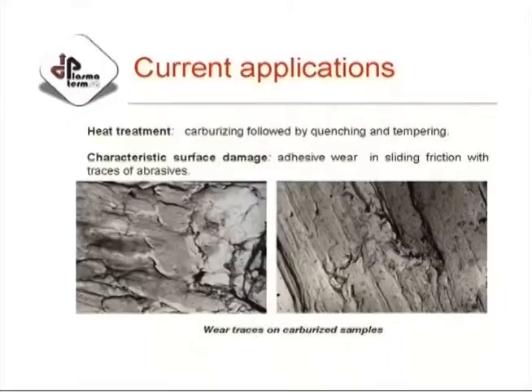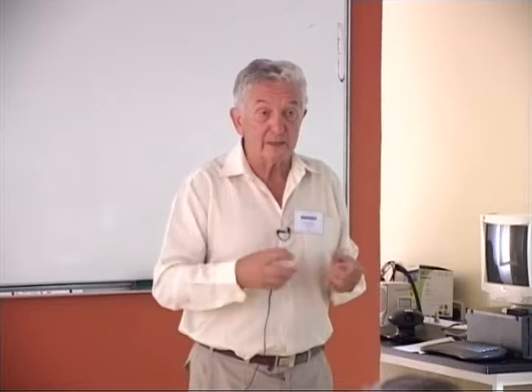I was given a task years ago to try to find a better solution, and then we tried to change this. It's just illustrating a scanning electron microscope picture of the worn surfaces. This is a very bad one. So when an advanced damage may be observed, this is not only due to the adhesive type wear, but also because of the high presence of some abrasive particles, because the polyacrylonitrile thread is something awful. During operation, very fine debris of this fiber are entering into the structure of the machine, and they have a very, very strong abrasive effect. It's one of the biggest problems with most of the textile machines.